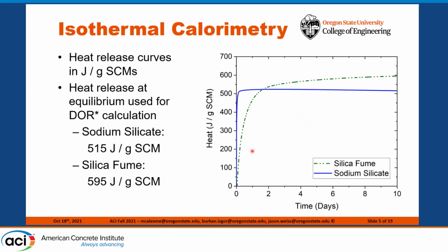The isothermal calorimetry results show just how quickly sodium silicate reacts, with most heat release happening within the first 6 hours. At equilibrium, sodium silicate produces 515 joules per gram SCM, and silica fume was slightly higher with 595 joules per gram. The curve of sodium silicate is actually preliminary data at this point.